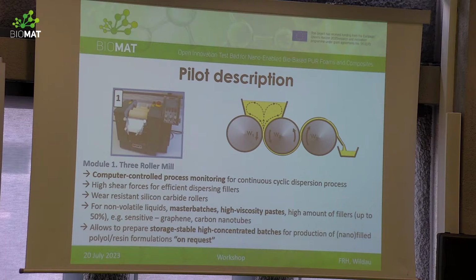Some words in detail regarding our line, regarding our modules. The first module is a 3-roll mill, and this mill is very effective for preparation of very high filler systems. We can prepare a system with a high amount of filler, up to 50%. We have computer-controlled processing, and monitoring during the dispersing. And what is very important, we can disperse very sensitive fillers such as graphene and carbon nanotubes without damaging them during the dispersing. Also, we can prepare storage-stable, high-concentrated batches for production of nanofiller polyol or resin formulations on request. We make a concentrate, and then reduce the amount by dilution in the next steps.